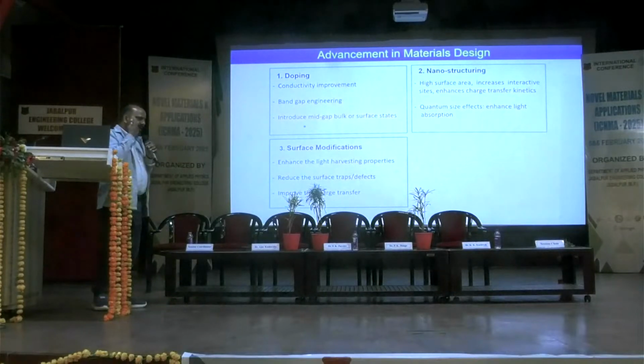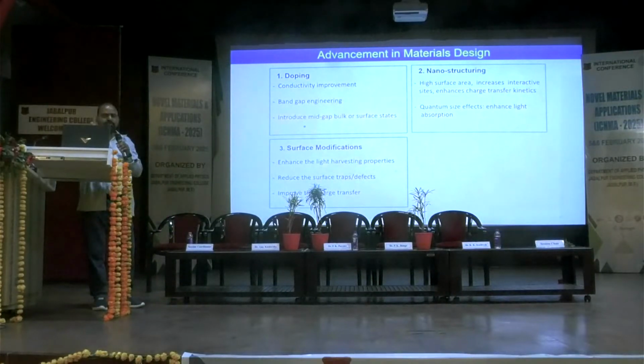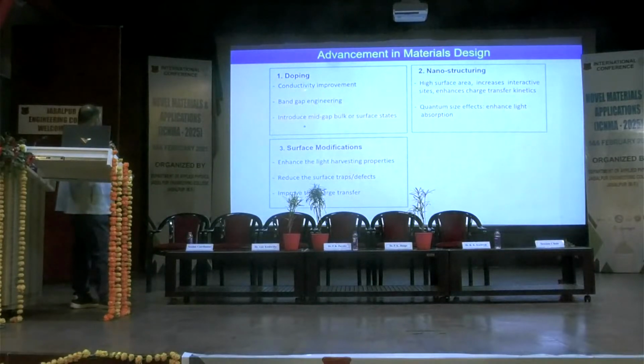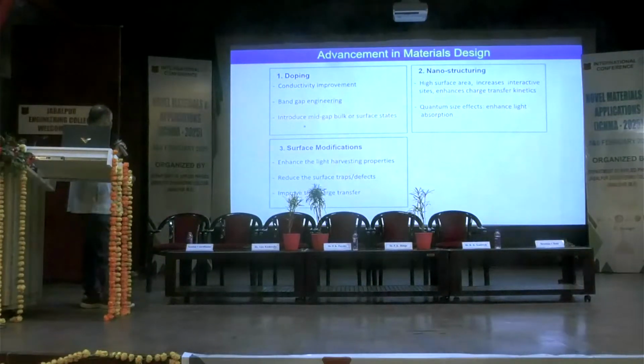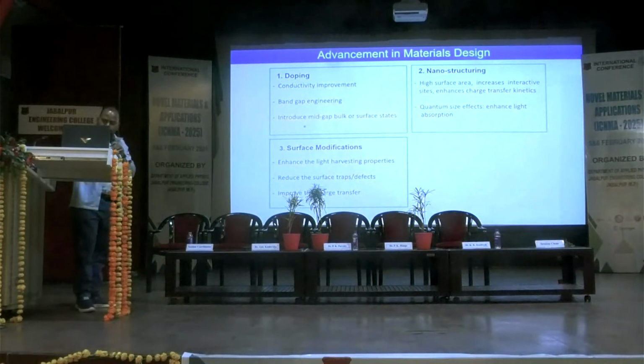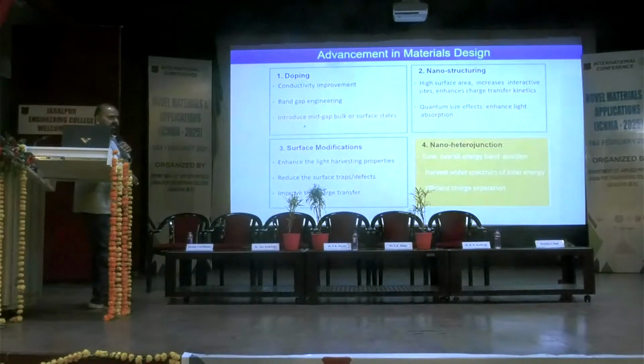So what was the generic philosophy or idea? If you look at the literature, you will see people are doing the same. Either we adopt doping of the material, so we can improve the conductivity and tailor the band gap, but it creates some defects which reduce the performance. Surface modification, as I showed, is also a topic which has been explored a lot, and everybody tries to develop different strategies. It is helping us, but it's still not so good. Nano structuring is another aspect which helps through high surface energy or surface area, interactive sites, enhanced charge transfer kinetics, and quantum size effect. They are good and helping us, but not as much as our expectation or at least the requirement.